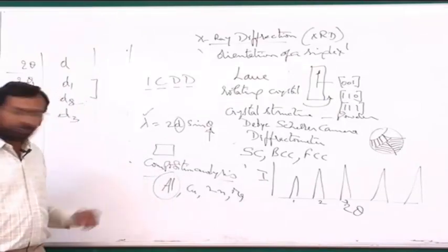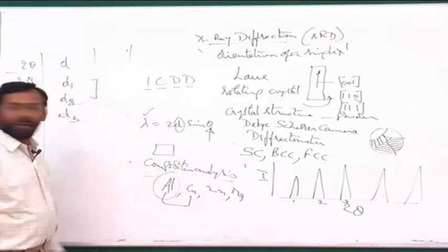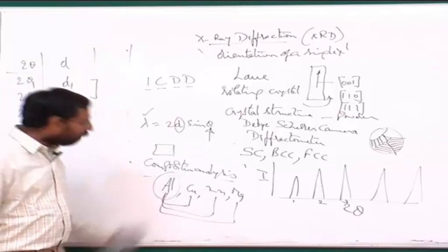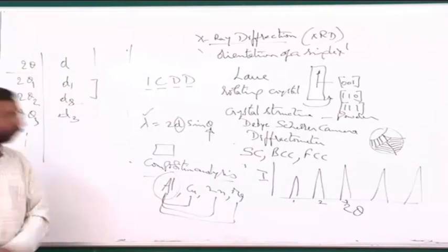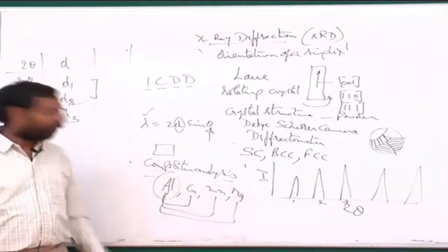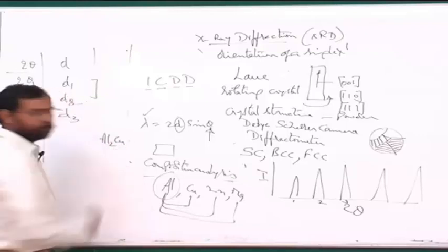Now what do I do? The next thing, I will try to go to the phase diagrams of these, aluminum copper, aluminum zinc, and aluminum magnesium. Let us say, if my alloy is showing these elements, then I go to those phase diagrams and find out what are all the possible compounds, if there are any compounds with these particular elements. For example, I know from aluminum copper there is a compound called Al2Cu.